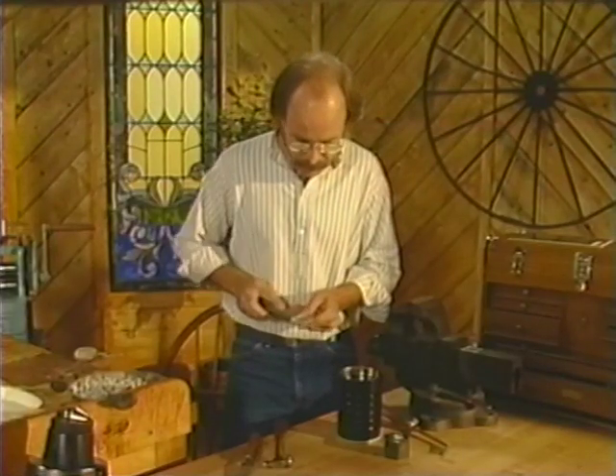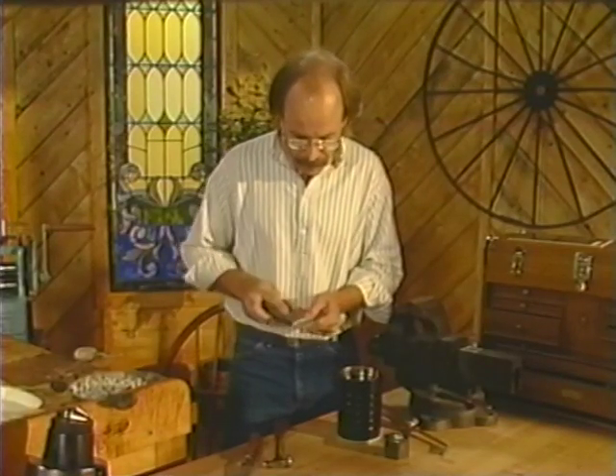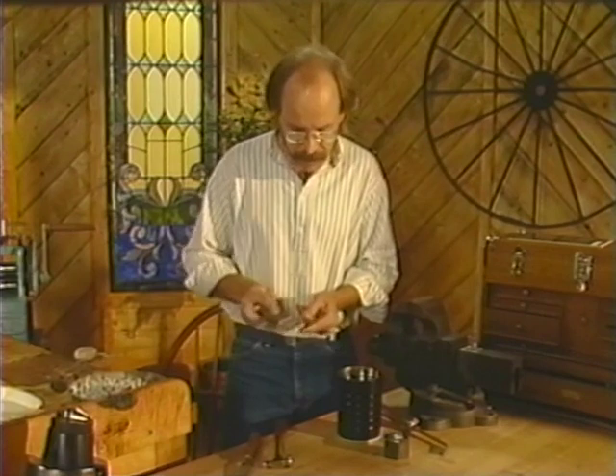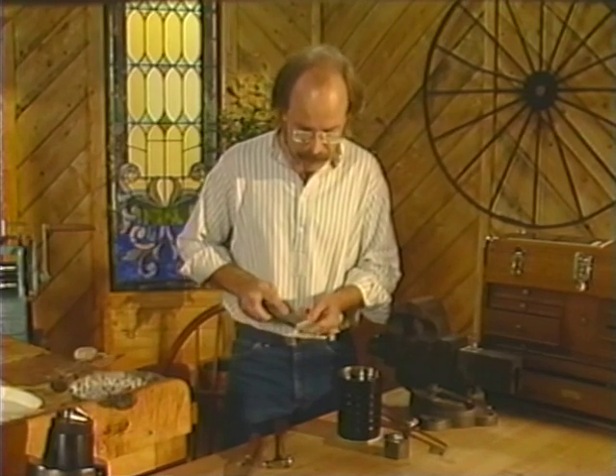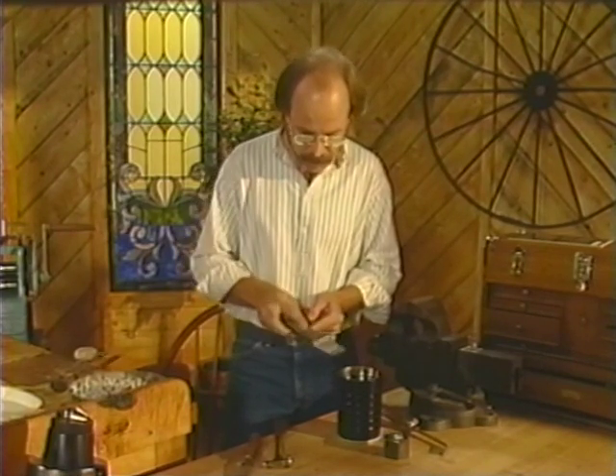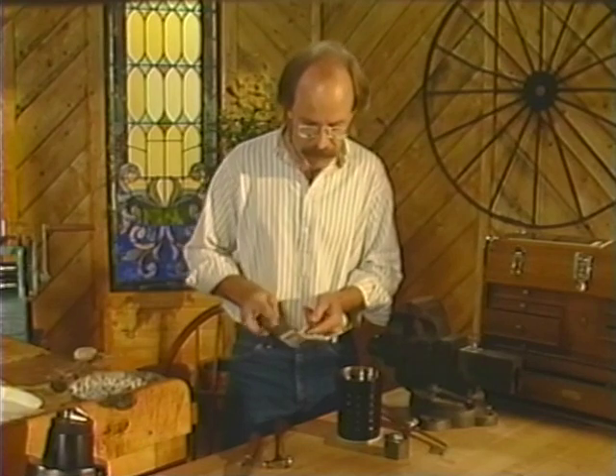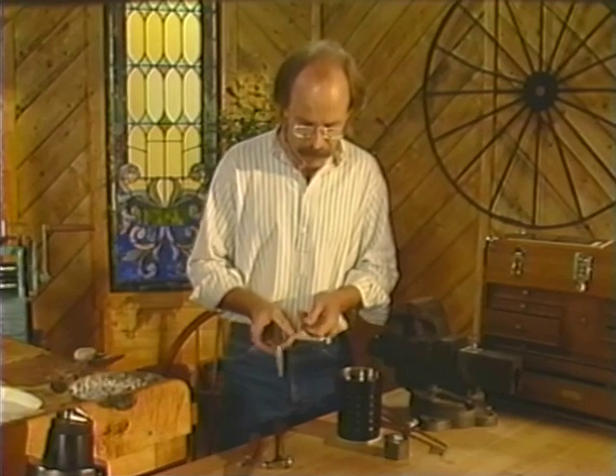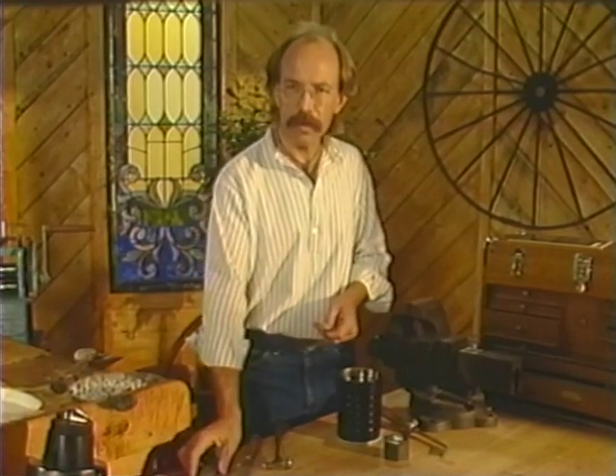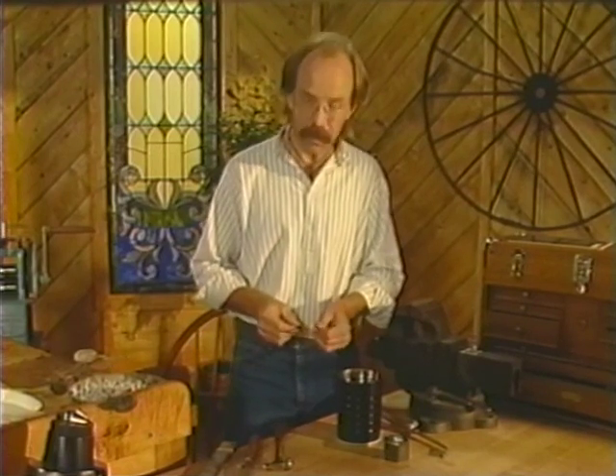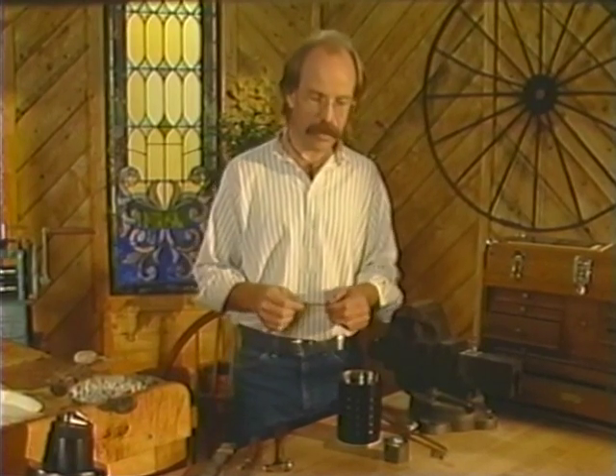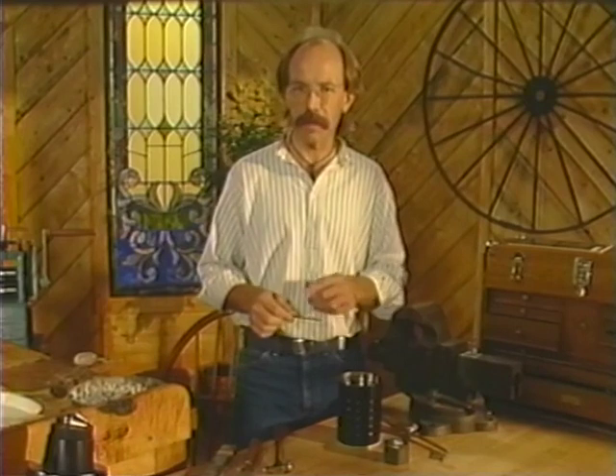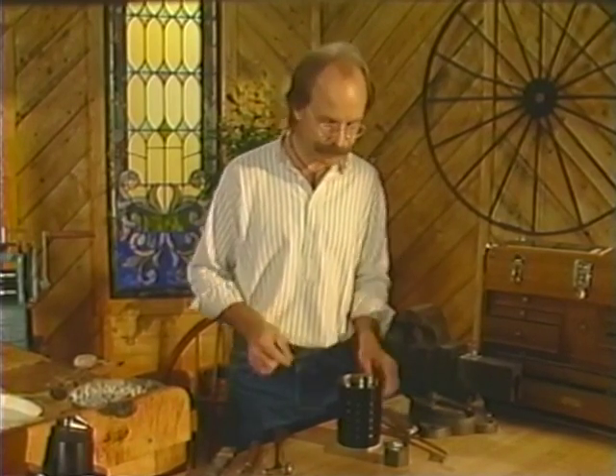The hardening process that went to bright red operates at a little over 2,000 degrees Fahrenheit. The tempering that we're about to go into operates between 400 and 600 degrees. For that reason, you'll want to use a small torch, a gentle flame, and go slow. I think if there's a single common problem, it's in running right through this process and missing it because it happens like that.